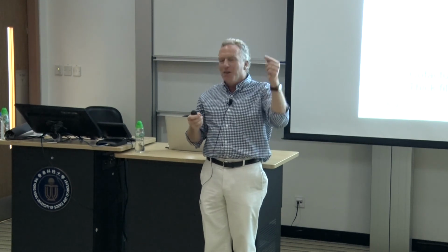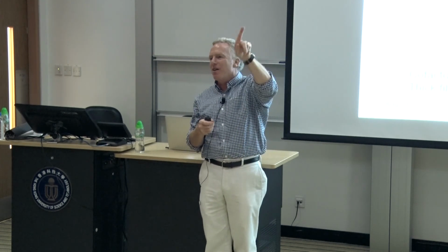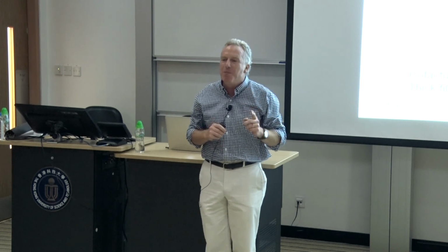There are certain points where there are little umbilical points. In other words, in those directions, you can hardly deform the crystal at all, if it does not satisfy the cofactor conditions. Now you turn on the cofactor conditions, and it interpolates those spots. So it somehow improves the deformations possible in badly oriented grains. That can be a very important thing. That's the only thing quantitative I think I know. I can tell you quantitatively something about that, but